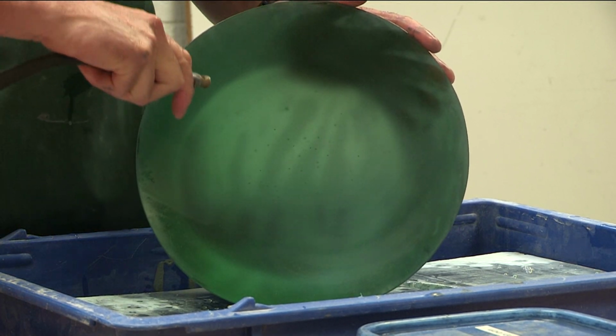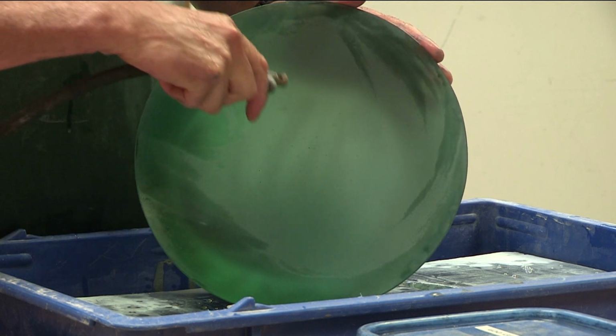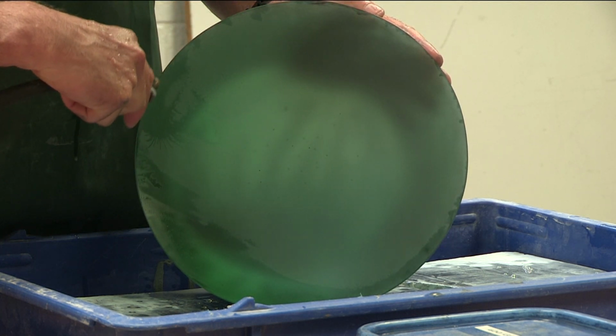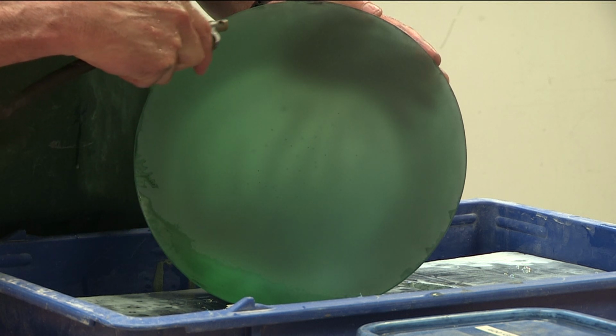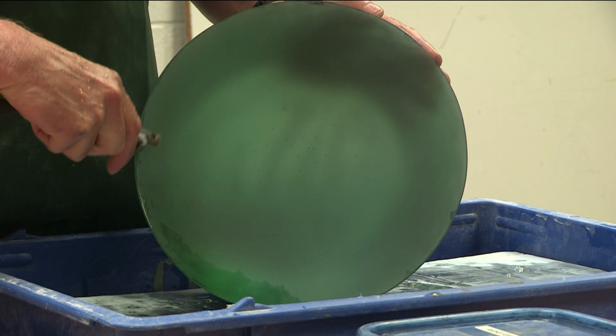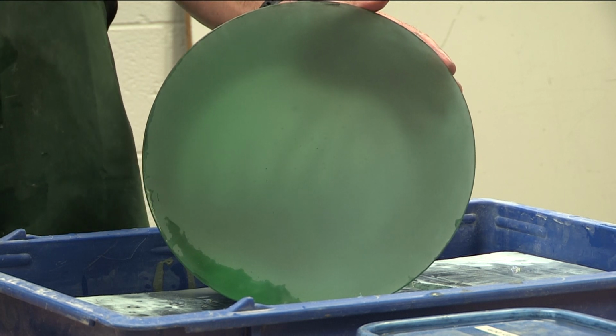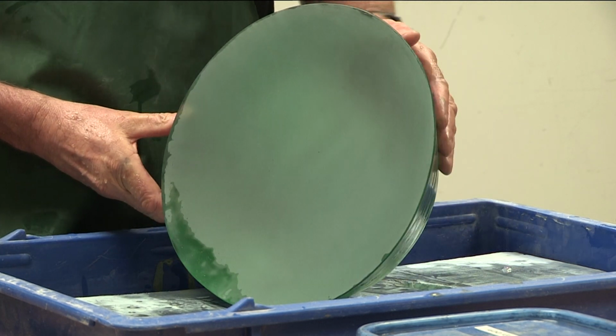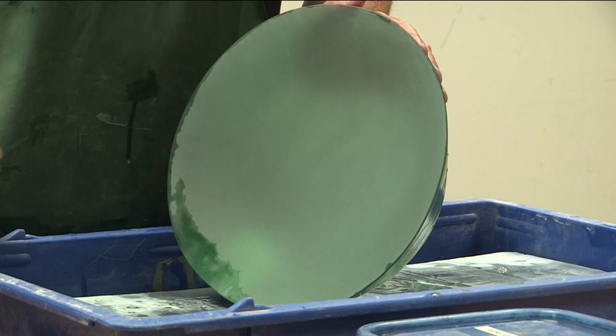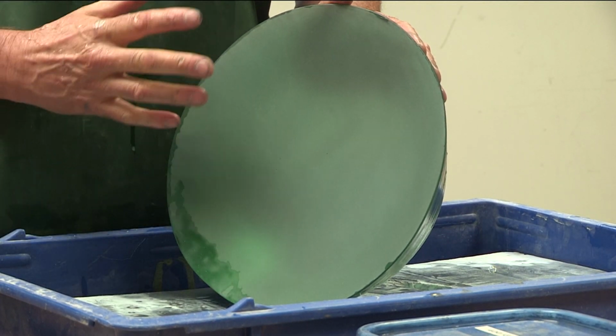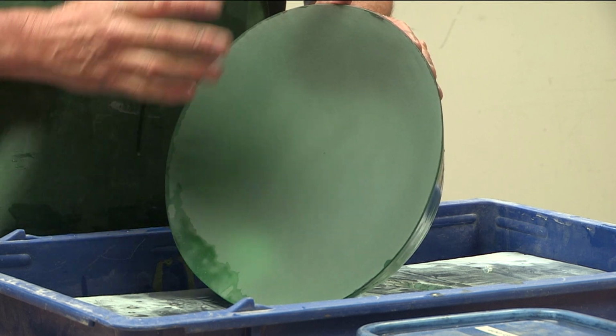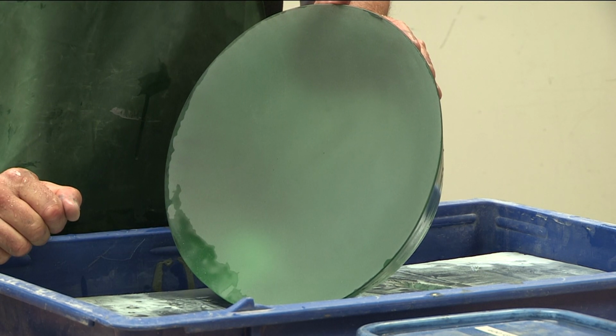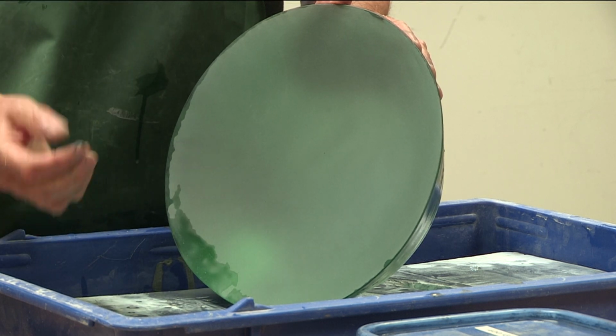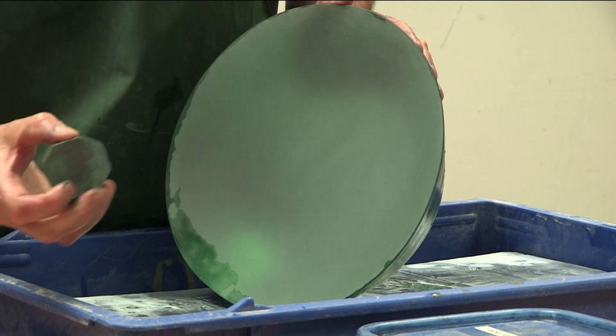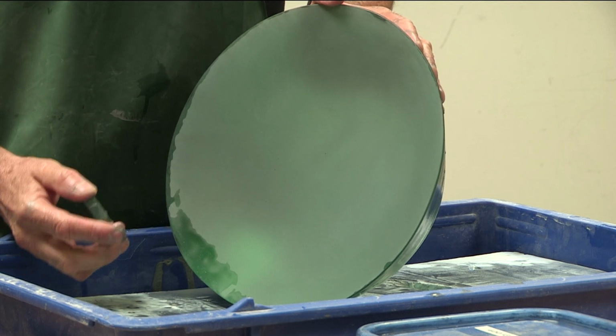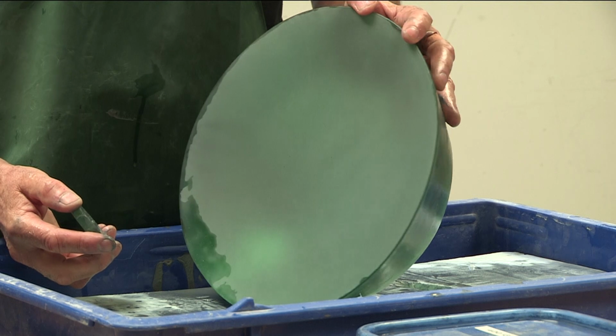Just use the compressed air for a second. And you can see that it looks pretty silky on that camera work. There we go, that's a pretty good angle of it. You can see there's a nice even surface there. That certainly didn't just take the 5 minutes that I took then to establish that. That took about 30 to 40 minutes of grinding, constantly putting fresh grit on. But it really is just the glass on glass, and it gives you that really beautiful, even finish.